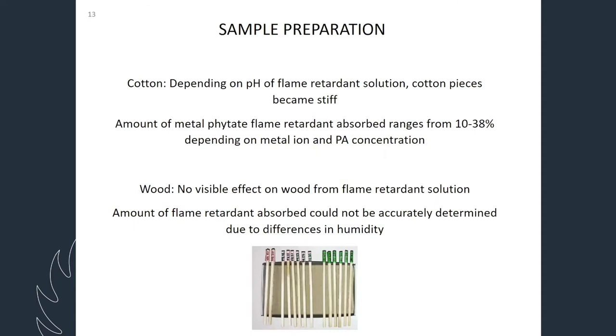However, we found that depending on the pH and sometimes the concentration, the cotton pieces can become a bit stiff. And if they have color, sometimes the pH can influence their color. The amount of metal phytate from flame retardant is around 10% to 38%, depending on which metal ion we are using and the concentration we are using. So if it is 10% solution, of course the weight increase is more. With the wood, there is no big effect. There is no visible difference.